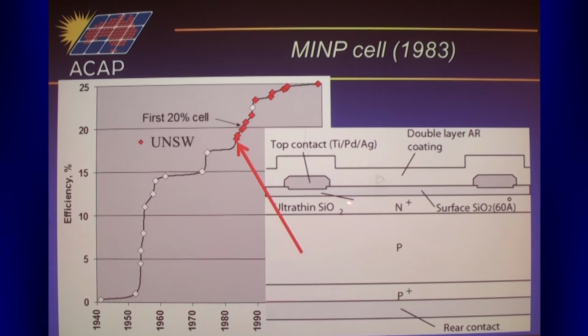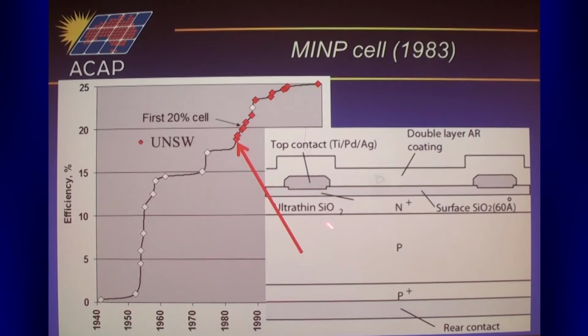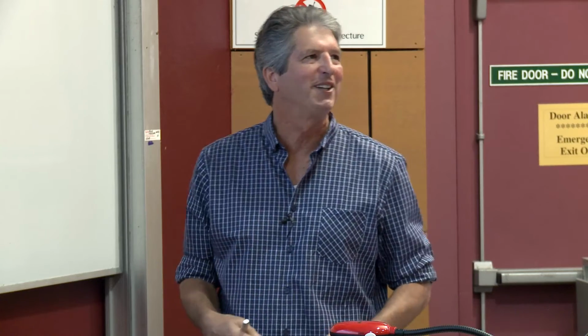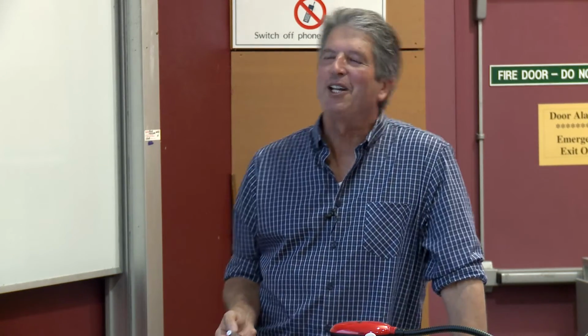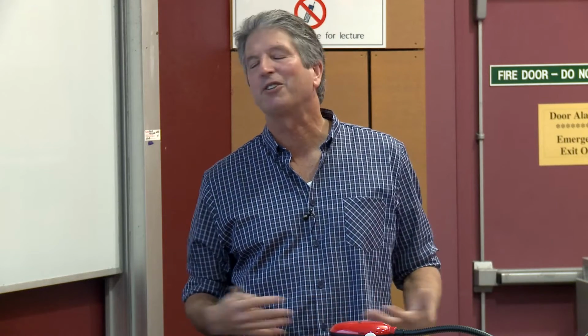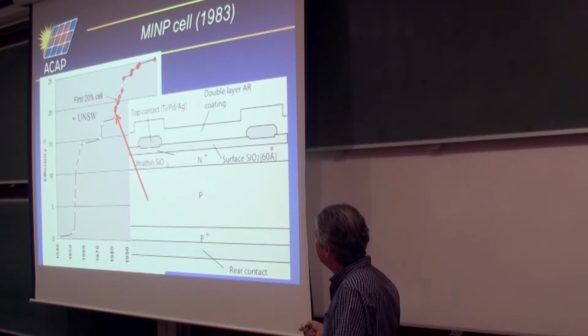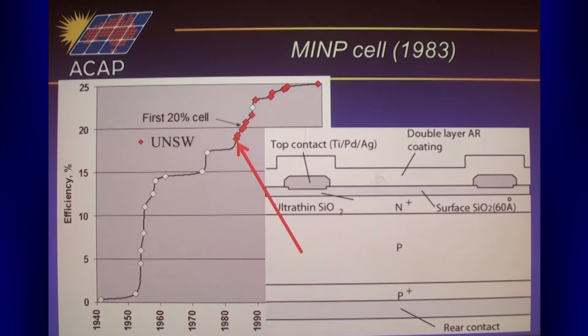It turns out, having a metal here and then an insulator and then semiconductor, you say, well, you mightn't get any current flow there because you've got an insulator, but we had to make these oxide regions very thin here so the carriers could flow through that insulator by quantum mechanical tunneling. So that's one of the successes of the quantum mechanics developed in the 1920s: it predicted electrons could flow through regions that were classically forbidden, and going through an insulator is classically forbidden, but if it's thin enough, the electrons can get through there. So it had to be about 2 nanometers, 20 angstroms, for that to occur. In this region here, we could have the oxide thicker, but you ran into different problems.